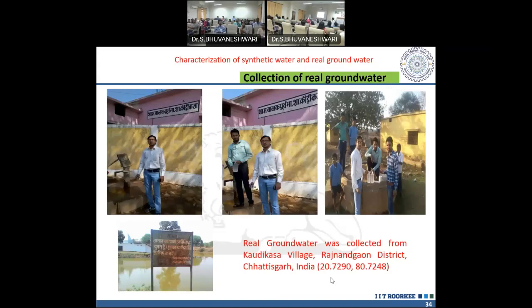Then that was used in our lab for the validation, and we found that what we were expecting on the basis of our lab, the same result we are getting with this one, even better result. Okay. Whatever removal we get with synthetic water, we are getting 1.5 times better removal in the real water sample. What is the reason? Because there are many other metals in the water that help the removal of the arsenic and fluoride. That's why we got that also.